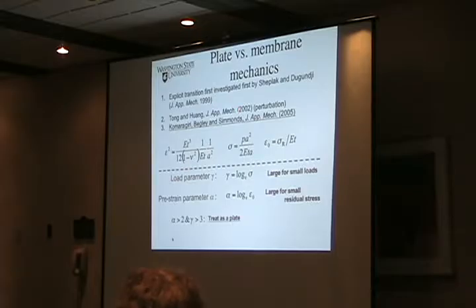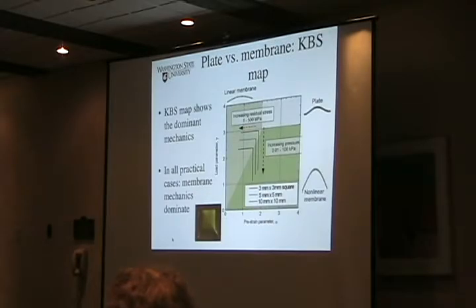And we go back and read things about people doing small plates as MEMS, straightening out to large displacements, and Begley's group in particular put a nice way to do it. That if you had residual stresses and residual strains, you could calculate, should you treat something as a plate or a membrane, depending on what these various parameters of stress and strain came out to be. And you can map out something like how much you're pressurizing the membrane on the back versus how much it's pre-strained. What you find out is that for every one of our cases where we actually operate the membrane to generate somewhere in the order of hundreds of microwatts, we actually come down here into a nonlinear membrane as opposed to our original plate model.